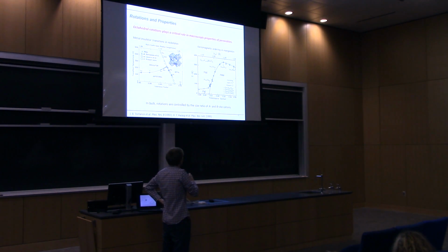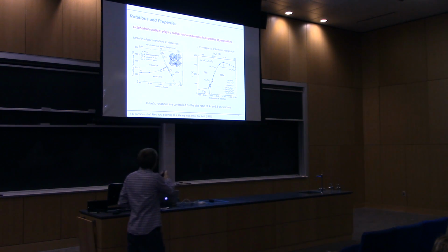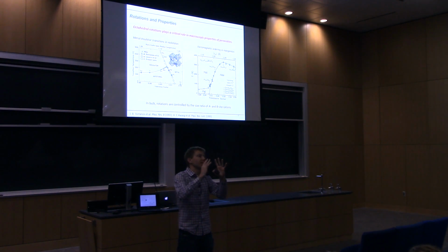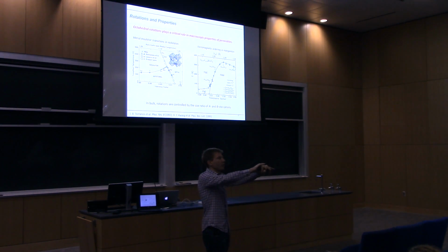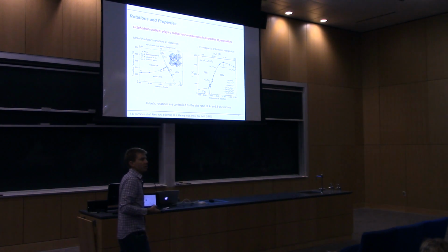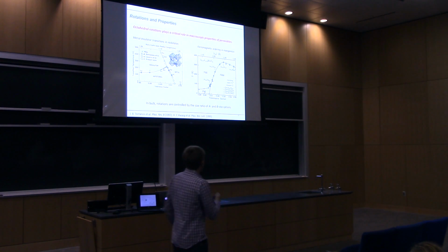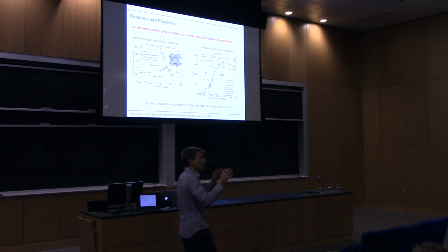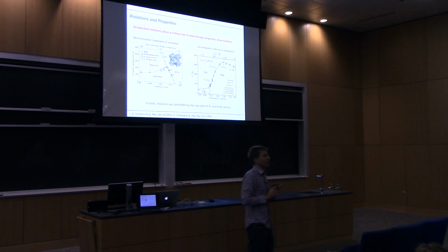Another example, and Rick showed this phase diagram as well, is ferromagnetic ordering in the manganites. So the canonical double exchange phase of the manganites, right? As I go from lanthanum strontium to lanthanum calcium to praseodymium calcium, again, I'm doing this chemical pressure trick where we're reducing the size of the A-site cation, shrinking the lattice, that cranks up the magnitude of these octahedral rotations, and that weakens the double exchange interaction because the carriers have less electronic bandwidth. Okay? And you can see the Curie temperature drop as you do that. Again, you're not changing the manganese nominal valence. This is all just from playing with this octahedral environment.